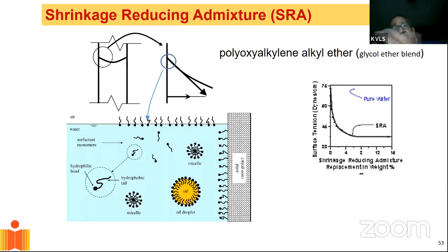Now, there are admixtures that are being developed to control shrinkage, and one of the admixtures that is being developed to control shrinkage of concrete is called shrinkage reducing admixture. And basically shrinkage is caused or produced because of surface tension effects of water inside concrete. And the best way to reduce shrinkage is to reduce the surface tension of water. So the shrinkage reducing admixture essentially reduces the surface tension of water.